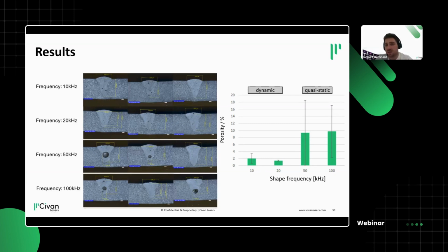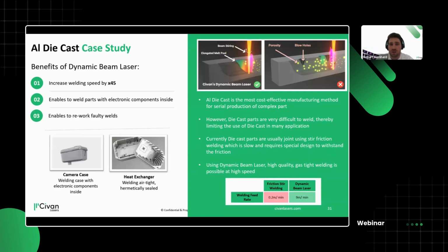Something we are really happy with welding aluminum die cast. It's fast, it's hassle-free, and you don't even need argon for these. So these are purely remote welding without any shield gas. And I think this sums it up really well. Compared to friction stir welding, we are way faster. Our dynamic beam lasers, 9 meters per minute, if not even faster. And I think this is a very good application that we also, in Hanover, are building our business on, expanding in this direction, doing more and more of this laser welding.